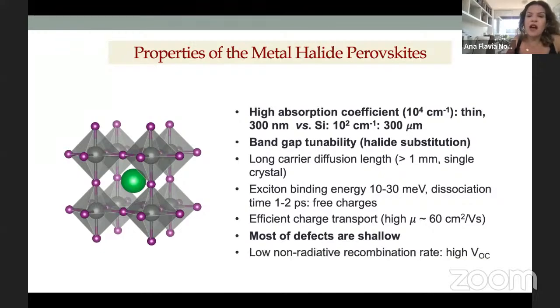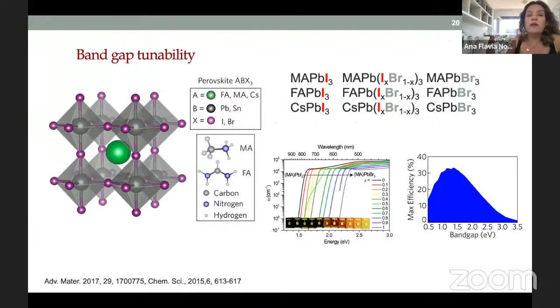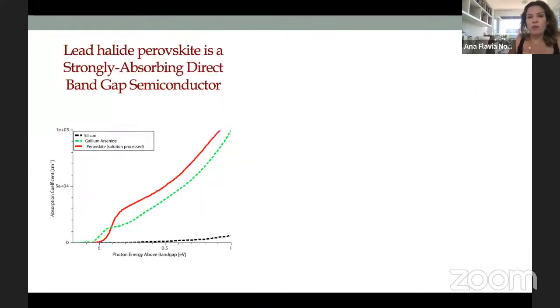First is the high absorption. Okay, first is the band gap tunability. Because you can play with the composition, not only changing the cations on the A site but also the halide, especially in this case here, when we are changing the halide composition, you can cover the whole solar spectrum. So this is really nice if you really want to tune the band gap of your material.